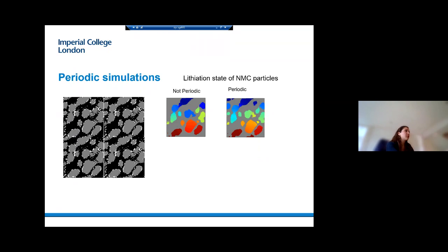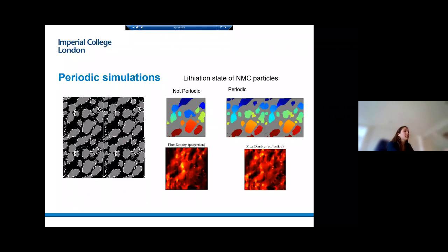So, for example, if you compare a non-periodic structure with a periodic structure, you can see that there's continuity in the transport properties from one side to the other. And if we see, for example, by calculating the flux density, where you see the red arrows, basically what comes out can come back in the next slide. Well, if you have a periodic boundary simulation and you put them back together, you can see that at the edges there are flux channels that have been opened. And basically, this is a more realistic representation of what's happening inside of the microstructure. And by doing this, we can actually reduce the size of the representative volume that we need for calculating microstructural properties or for any type of simulation.